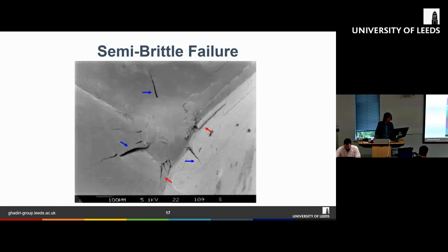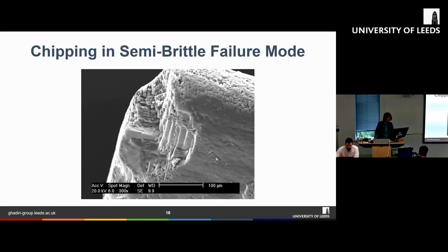So these are examples of materials which undergo semi-brittle failure. You can see here at the impact site, very obviously, the material gets flattened, so you can see some sort of plastic deformation. But we also see different crack systems here. For example, here you can have a median crack or radial crack, and then here we also have a subsurface lateral crack. And here's another example, which shows the chipping of the corner of a particle.